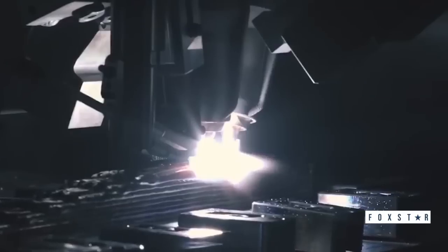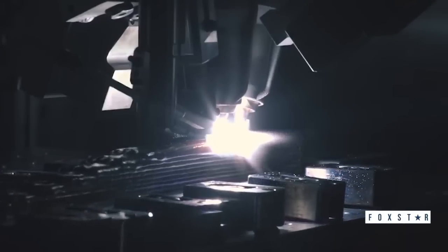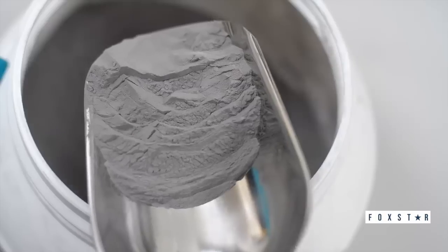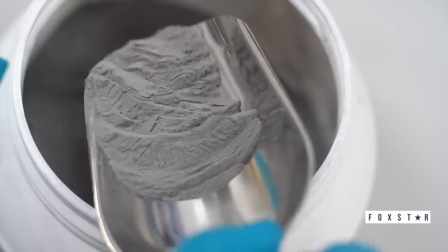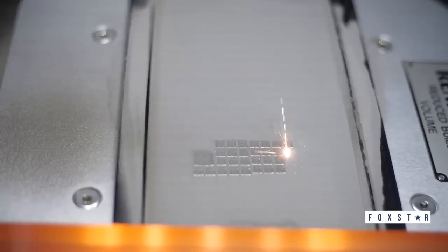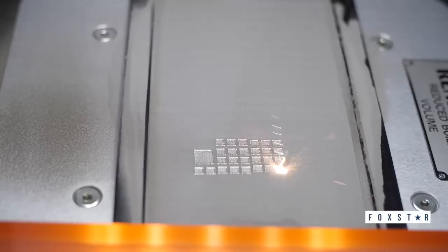Now, making 3D printed metal parts is not easy. Most titanium 3D printing involves a powdered titanium that is melted together using lasers. Researchers used high-speed X-ray imaging to visualize what happens during this process and found a lot of imperfections. The track varies in height, the powder gets blasted away, resulting in varying thickness and separated tracks, and even bubbles form, causing pores in the metal.